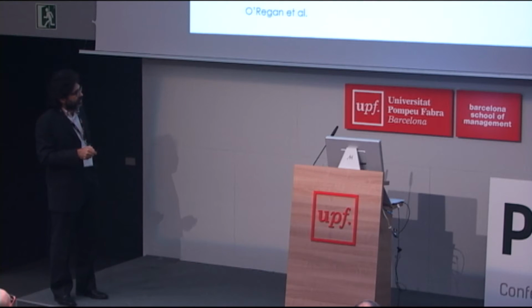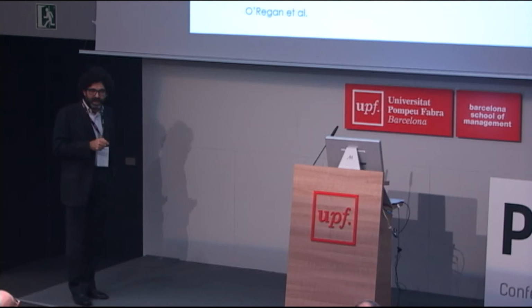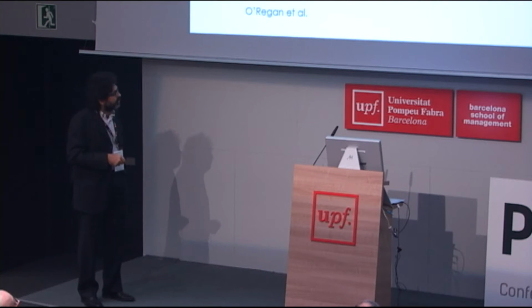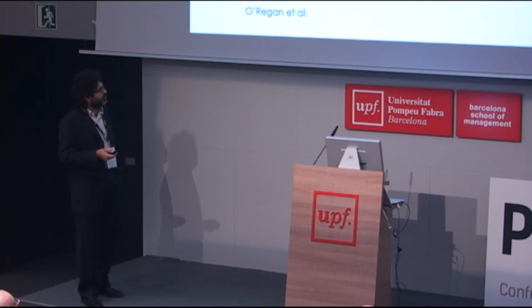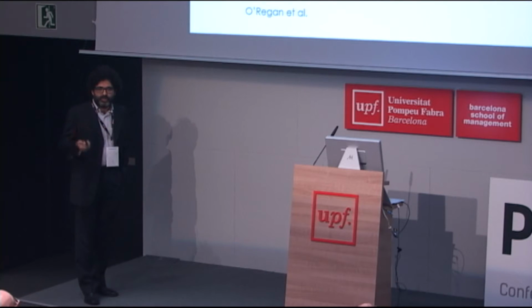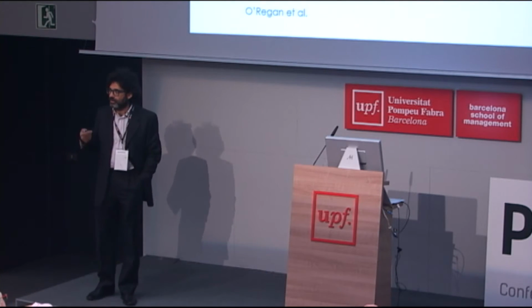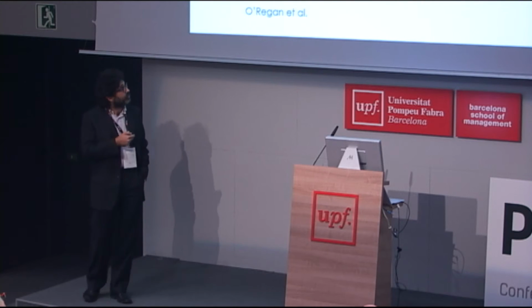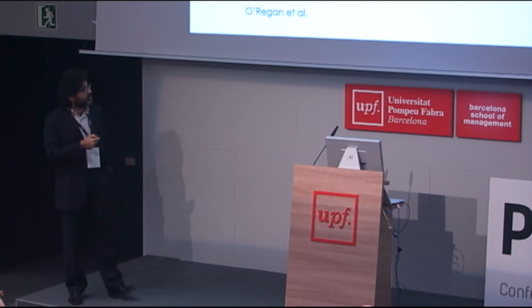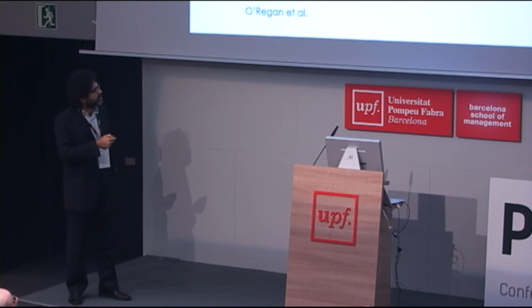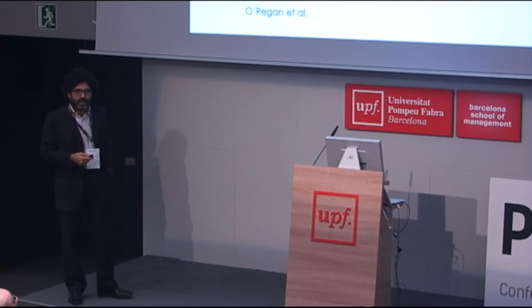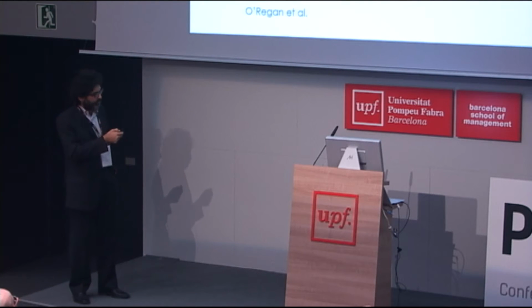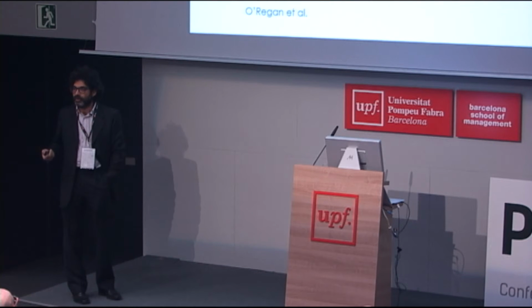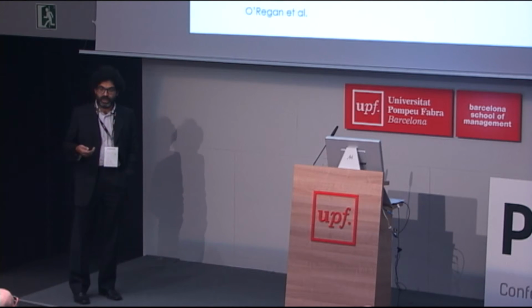So in 2005, Peidong Yang was suggesting to use single crystalline nanowires with much increased mean free path for electrons. And as Professor Morante was saying, nanowires have a pretty high surface to volume ratio, which is true for gas sensing, but it is not true for solar energy. If you compare the specific surface of nanowires to a mesoporous nanoparticle structure, it's at least one order of magnitude lower. So you can transport the charge very well, but you cannot have the optical density you need to efficiently absorb the solar radiation.